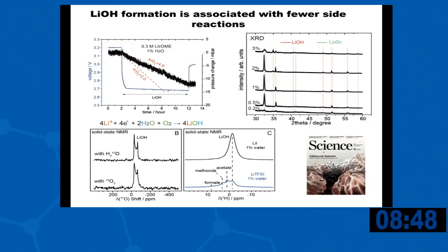This is a more clearer spectrum. So this is the hydroxide that's formed with water. If we remove the lithium iodide, you can see instead of forming hydroxides, we form peroxides, but we also get significant decomposition products. We can follow the mechanisms of where the hydroxide's coming from by doing oxygen NMR. So we prove that the oxygen comes from both water and oxygen via this oxygen NMR signal. And we can track whether this is a 2-electron mechanism or 4-electron mechanism by doing these pressure cells.